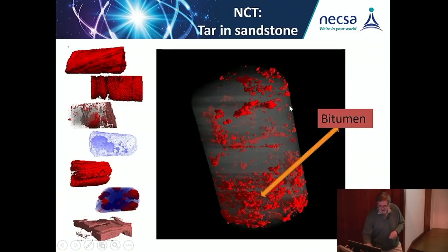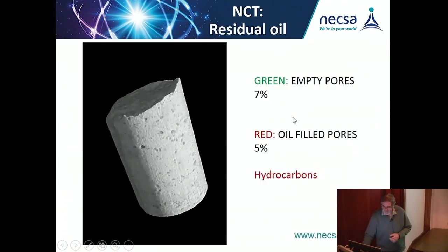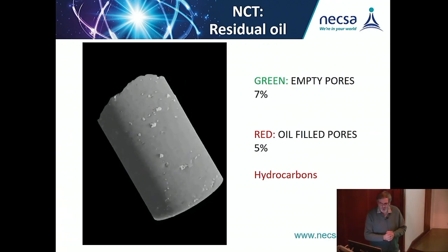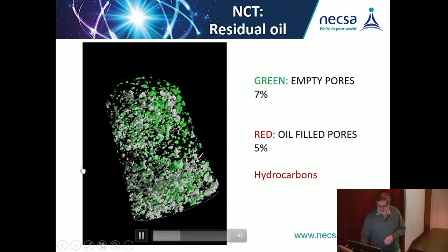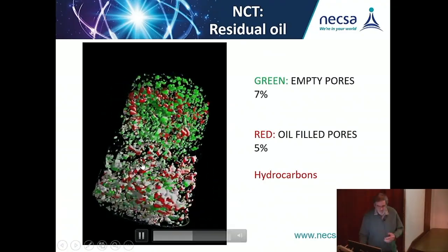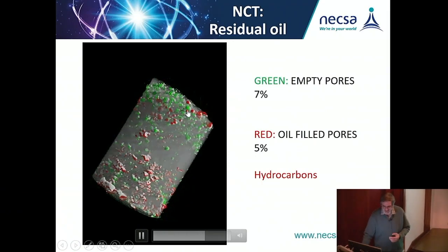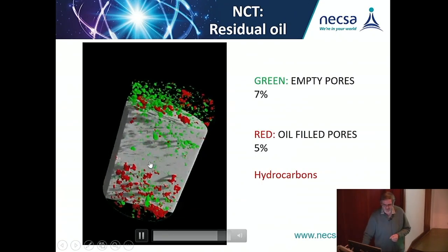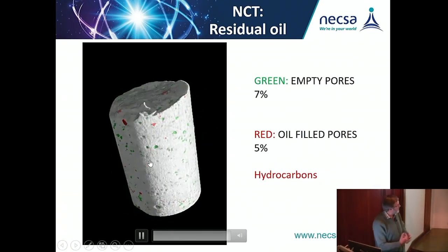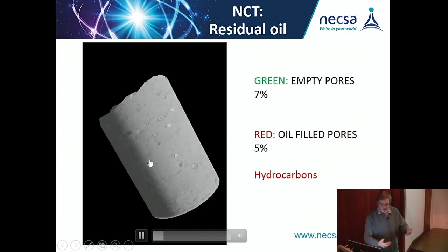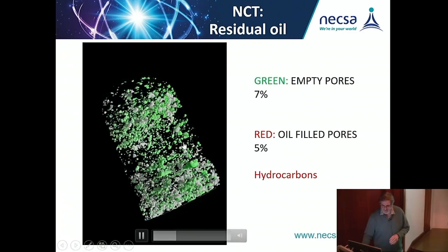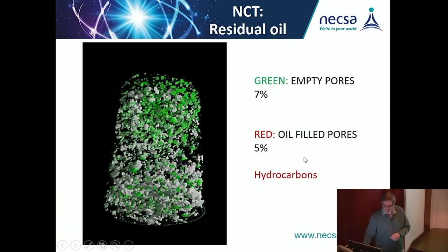Tar in sandstone. How much tar is available? Again, the hydrogen signal, because the NCT is neutron CT, shows effectively your bitumen in 3D. Here we have a residual oil in a sandstone sample, where the green empty pores one can quantify. So with 3D, you can quantify the whole volume, about 7% of empty pores, while oil-filled pores hold residual oil that is still available within that core, which can still be extracted. These are really available and can also be detected and quantified at the end of the day.